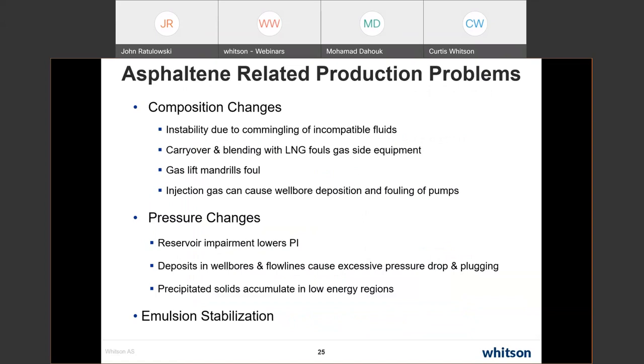So asphaltene related problems: composition changes can be caused by instability due to commingling of incompatible fluids, carryover and blending. We've seen gas lift mandrels foul because the injection gas is not compatible with the produced fluid, and also injection gas for EOR. When it breaks through, we see a lot of wellbore deposition and sometimes fouling of pumps. With pressure changes, we can see reservoir impairment in some systems, which will lower PI. Deposits in wellbores, and occasionally flow lines, can cause plugging.